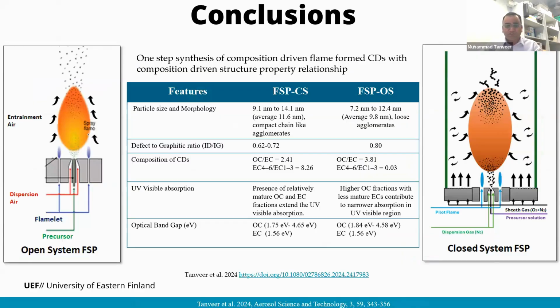So let's move to the conclusion part. This study basically gives a pathway for the one-step synthesis of carbon dots through flame pyrolysis and derives the structure to property relationship for the synthesis of these nanostructures. In the case of the open system, we have a comparatively narrow band gap and smaller particle size compared to the closed system. And in the closed system, we have more graphitic particles compared to the open system.